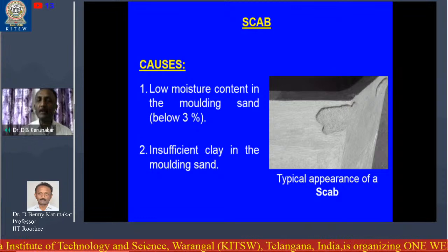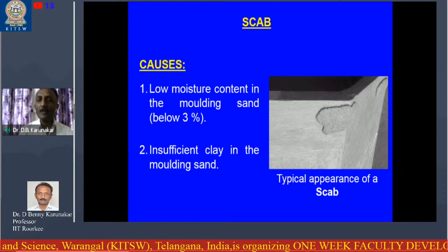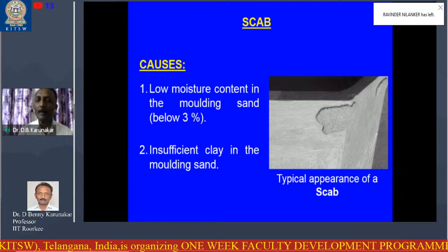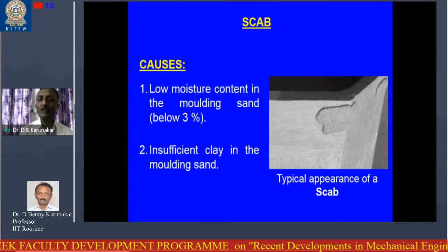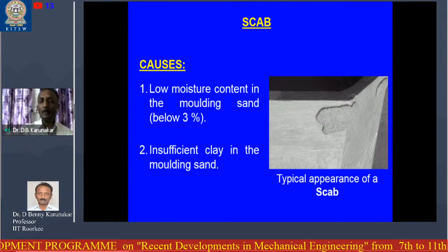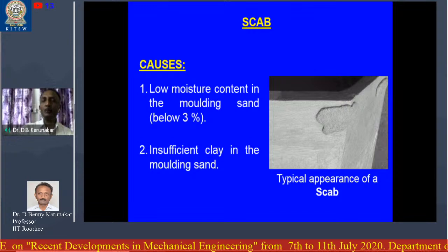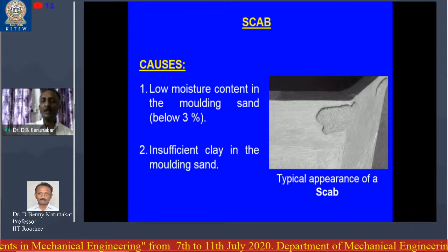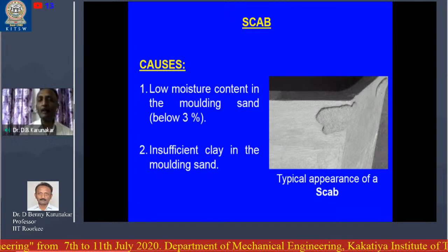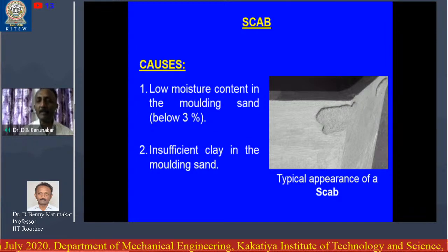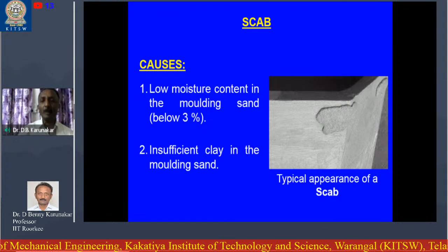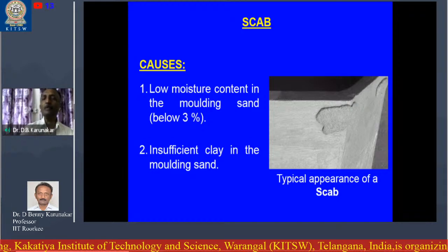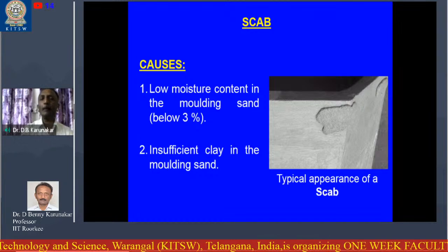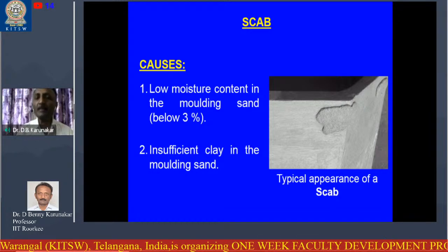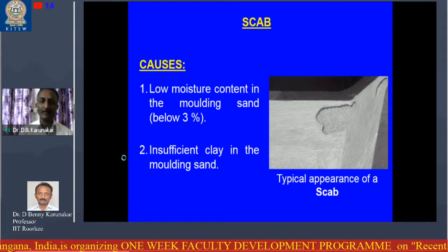But it so happened that moisture content is less and clay content is less, so the sand particles are not bound perfectly. They are loosely bound. So when you pour the molten metal and it flows through the gating system, as it passes through, it pulls the sand particles because they are loosely bound. Those sand particles are carried along with the molten metal into the mold cavity, and they are deposited and solidified on the surface of the casting. That is how the problem arises.